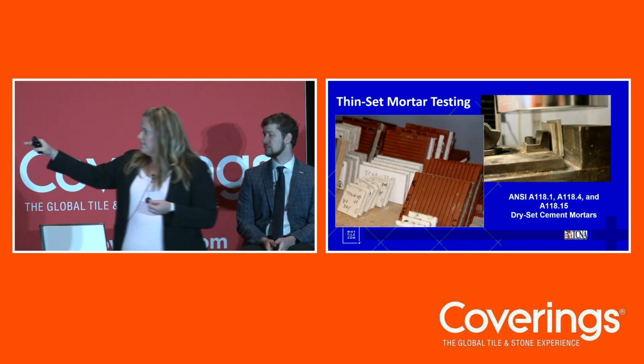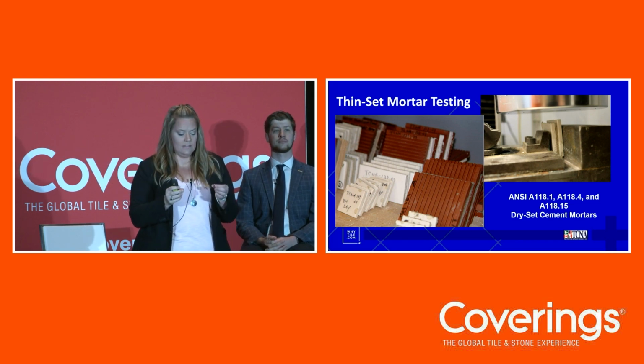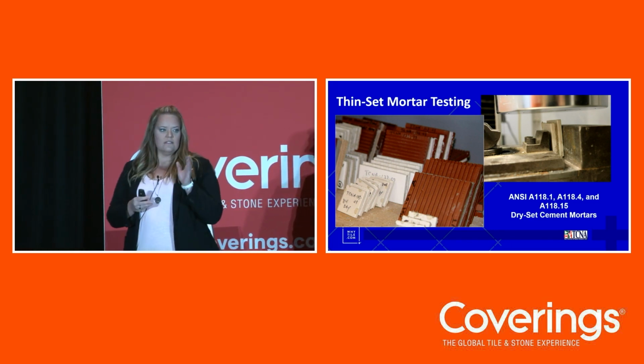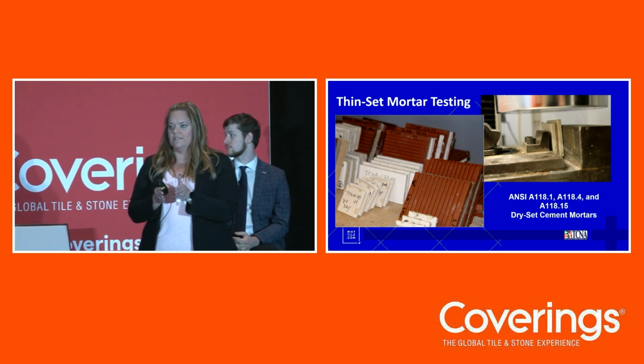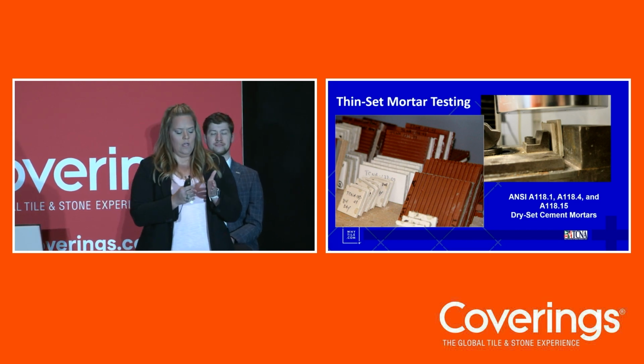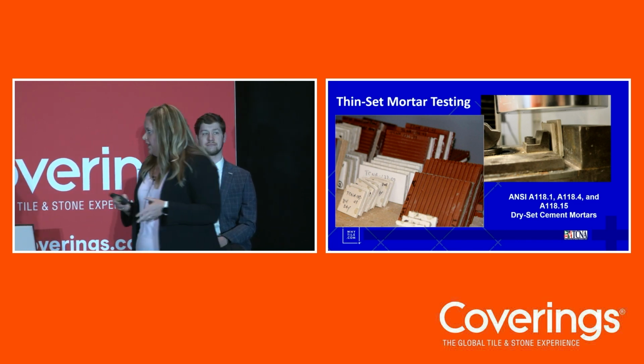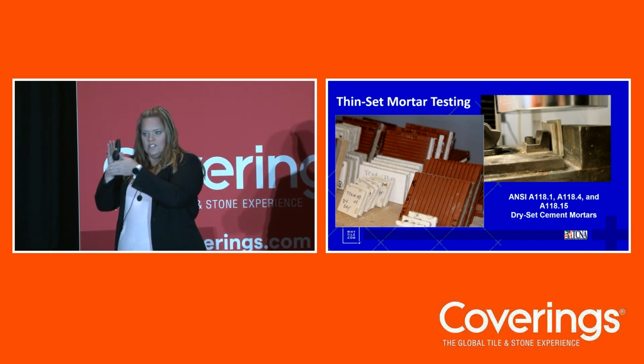So you can see in the sample picture, we have samples that are created where we have a specific thickness of mortar that is applied between the tiles. And we're using 2 tiles instead of bonding it to some kind of substrate because we want to control what we're testing. So we are just testing the thin set in this case. And so you just do face-to-face of the tiles, so you have a smooth surface, and that's not changing the result in any way. And then we put it in this fixture, apply load to that top tile until it shears apart.